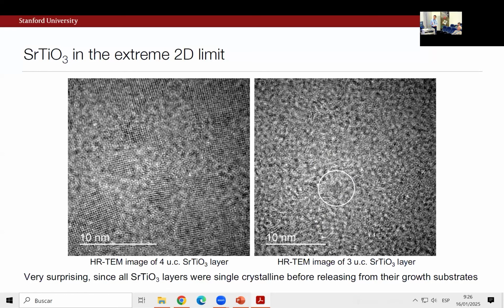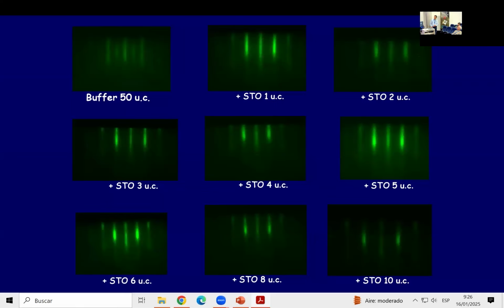What was most surprising to us was that all of these layers were single crystalline before we released the structure. We're growing at fairly high temperature, but somehow by dissolving this interface layer, by releasing this membrane, something dramatic happened. To give you one way to sense or prove that this thing was actually crystalline in the initial state, these are, again, reflection electron diffraction images of the crystalline buffer layer growing 1-unit cell of strontium titanate, 2 and 3, 4, and through the series, right? You can see this very nice coherent diffraction, and yet somehow by dissolving this layer out, we had this abrupt transition in the apparent crystallinity.